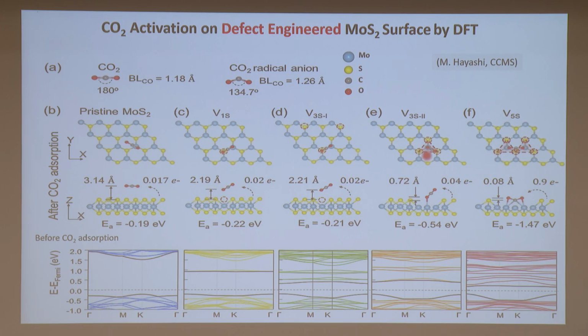Now, if you have a 3 vacancy cluster or even 5 vacancies, now the CO2 starts to shake hands with the material. With 5 vacancies, they really shake hands hard, okay? They have been bent, in the bent form of CO2. This is called chemical bonding. And with all these, actually, you can see the energy structure is already changed significantly, from a larger band gap with a little bit more gap states, and the more you do, the more you change the band structure.